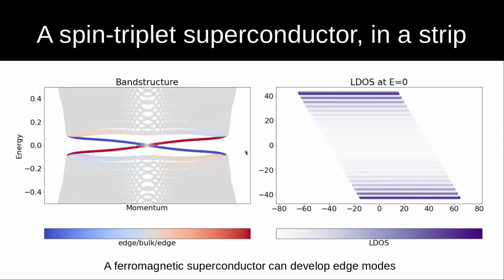Now, something massively interesting about this spin triplet superconducting state is that if you look at the electronic structure of the superconductor in a finite geometry, in a ribbon, what you actually see is that in the bulk there's a gap, which is what you see over here. But then at the edges of the system, you actually have gapless excitations.